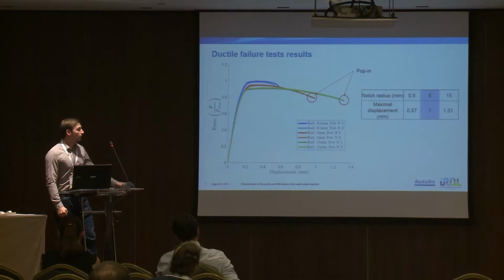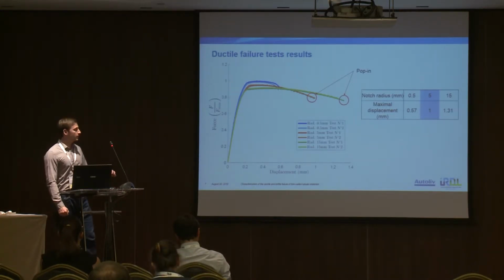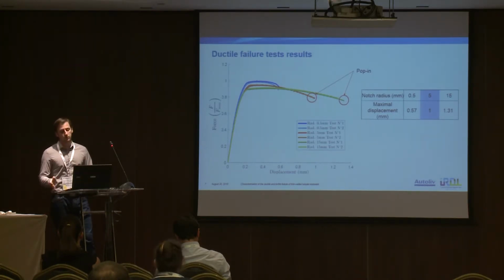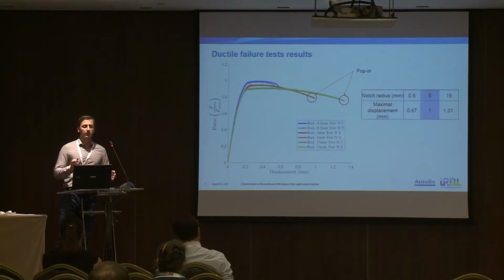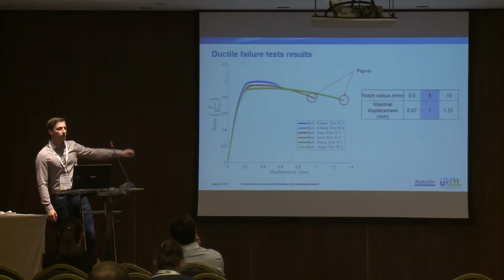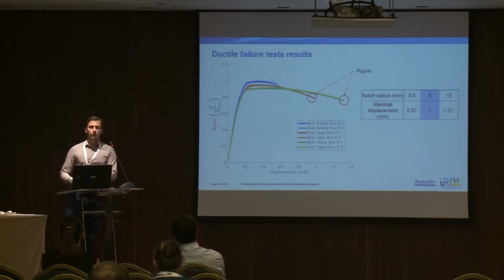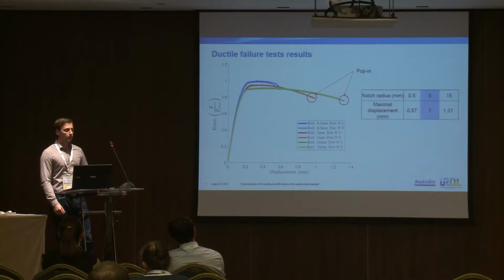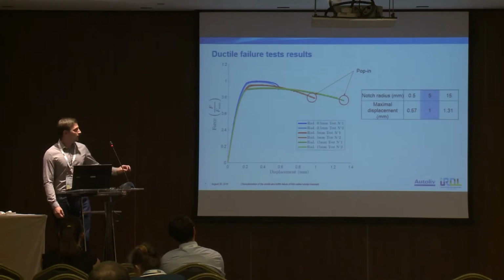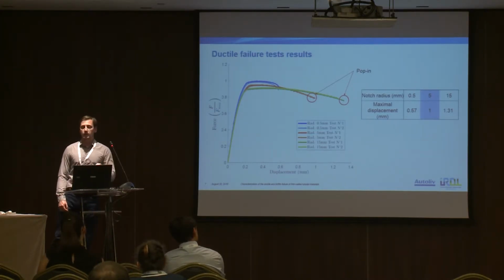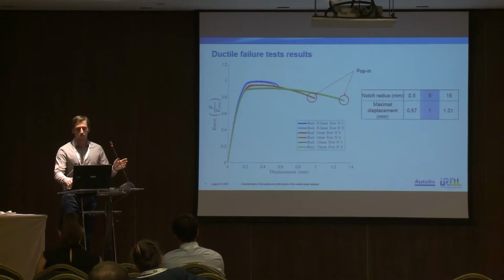Firstly, there is a pop-in phenomenon which occurs during our test. This is due to the very low ductility of our material. But in order to determine the maximal displacement, which is not given in this graph, we used a different approach in order to have a high sampling frequency on our test. So, with this kind of methodology, we were able to define the maximal displacement at coalescence, and then we were able to determine the damage parameters much better.